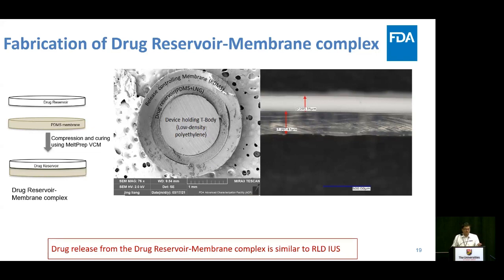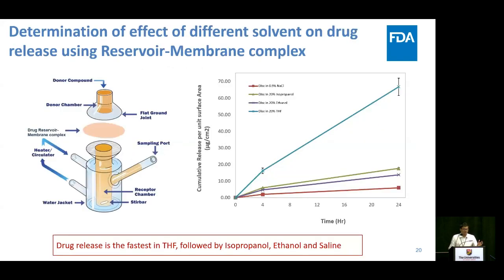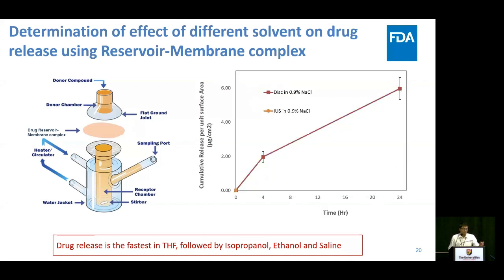And then we use this device to do short-term accelerated release studies in different solvents. As you can see, the prediction that we had from HSP analysis also supports our experimental data here. But most importantly, when we compare the drug release from the IUS device itself to the disk that we made in normal saline and normalized by the surface area, it is exactly the same. So it also proves that the device that we fabricated is maintaining the drug release mechanism of the IUS device itself.